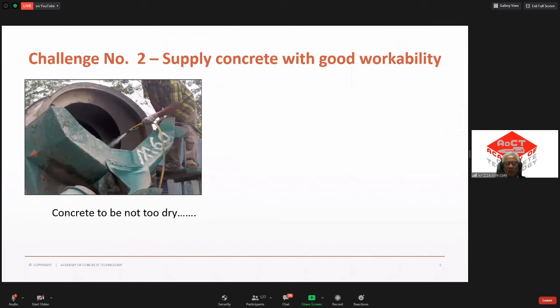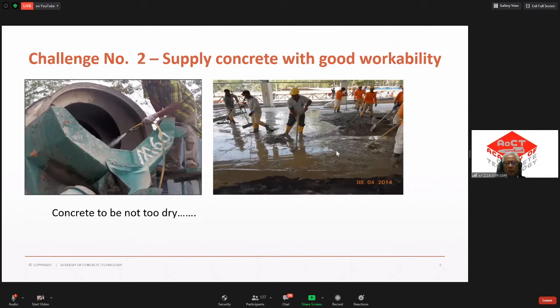So my recommendation is always good to have some superplasticizers at a job site on standby. If you find it's really too wet, you can always dose in, with the technician's advice on how much you could add. So this is the picture of what happened. They add water, right? So these are the earlier batches they have done, right? Looks good, workable, and this is after adding water. You can see how wet the concrete is. So besides all the consequences I mentioned earlier, sometimes because this concrete has already started, it will definitely set much faster, and this being wetter, it will definitely set slower. So as a result, you might have what we call a cold joint, right?